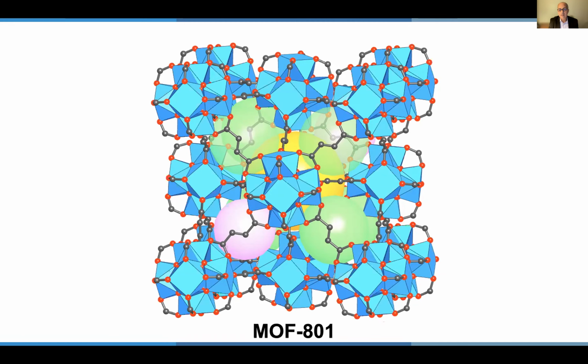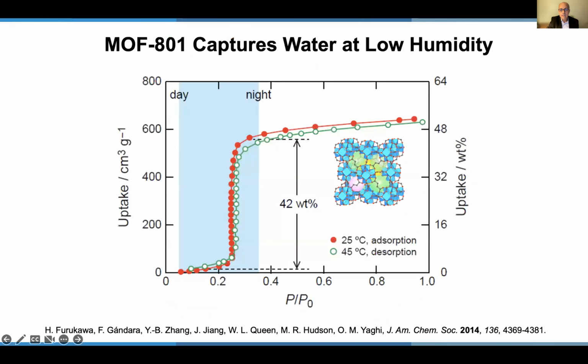Well, the way we discovered water harvesting was with this MOF. We call it MOF-801. It's shown here. You have the metal oxide units, zirconium oxide in blue, linked by these squiggly lines, the organic molecules, to make a porous structure. The pores are illustrated in pink, green, and yellow. That's where the water ultimately resides.